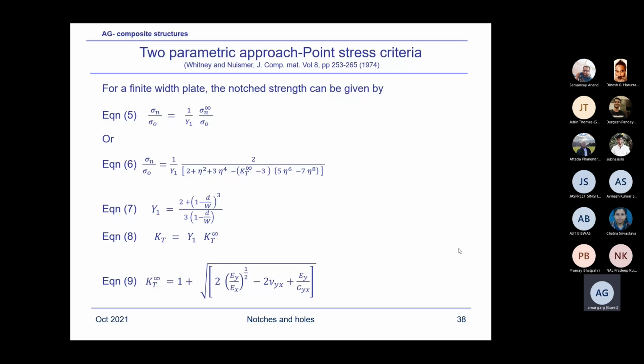I can discuss the criteria for certification. For delamination, we don't use a rate of delamination propagation and work out an inspection plan like in metals. You see, the purpose of crack growth rate prediction in the metallic structure is to develop the inspection intervals for maintenance and to understand when the crack will grow and reduce the residual strength of the structure below the regulatory requirement, which is usually the limit load.